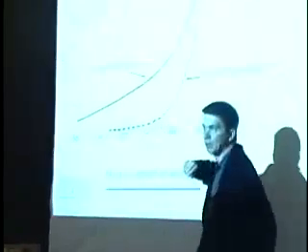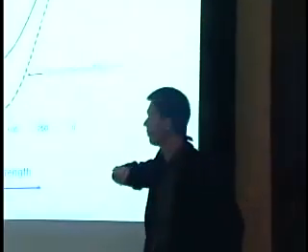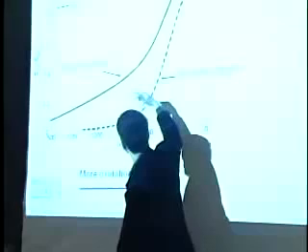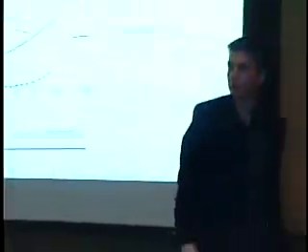But you can actually track the amount of ruthenium segregating to the surface, and as you bring more oxygen to the surface, you actually start increasing the amount of ruthenium in the surface as well. And so you can really solve the thermodynamics of these problems by ab initio methods, by going through this cluster expansion approach. You can actually look at the sites.